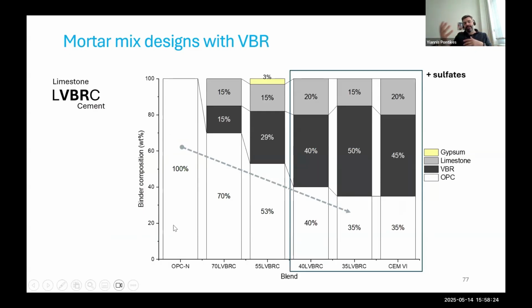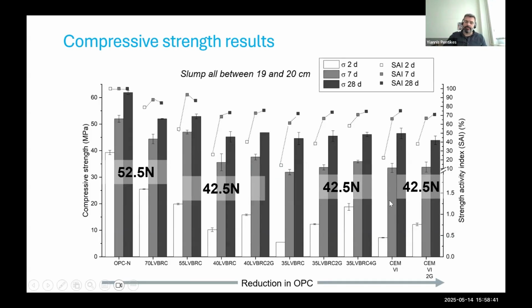Then what you do, you make the blended cements. You want to provide this whole range of formulations. So you find here 70% of cement, 30% of your additives. Here is limestone and VBR. And then you increase; you see the colors, with the dark gray is VBR, with the light gray is limestone. And then you see performance.